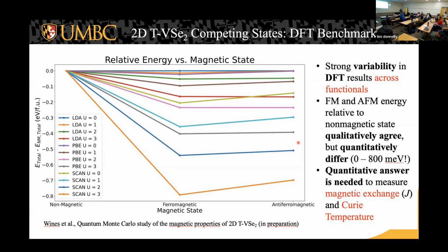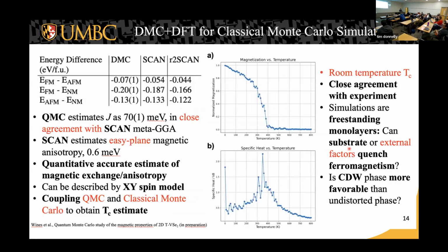So we managed to calculate the Heisenberg exchange parameter J with quantum Monte Carlo, and we figured that it is relatively large compared to manganese oxide that we previously found here. And when we benchmark our results with the other functionals as well, we find a nice trend here. SCAN also gives relatively similar values for our Heisenberg exchange parameter for this one.